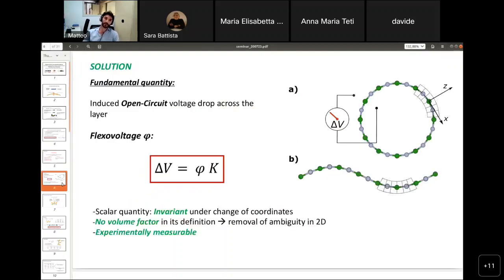Well, the solution comes with the electric potential. Why? Because the electric potential exactly solves all the problems that affected the polarization. Indeed, first of all, it is a scalar quantity. That means that the electric potential is invariant under change of coordinates. Secondly, there is no volume factor, so we have removed the ambiguity about the volume. And then, nicely, it is experimentally measurable. That is what people usually try to measure in an experiment done in a two-dimensional context.